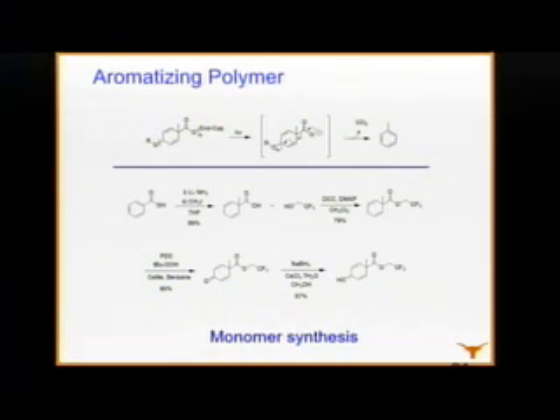So it was hard to make this monomer. We do a Birch reduction and alkylation. This reaction was hard to optimize, and a student came back and told me that he had found how to make it work properly. You need to add a little water. I'm going, excuse me? You added water to this lithium metal dissolved in liquid ammonia, and you didn't come to see me before? You're going to be punished. And anyway, yeah, if you put a little bit of water, you have to use wet THF, or it doesn't really work very well. But if you do, wow, it's great. You can get this diene in high yield.